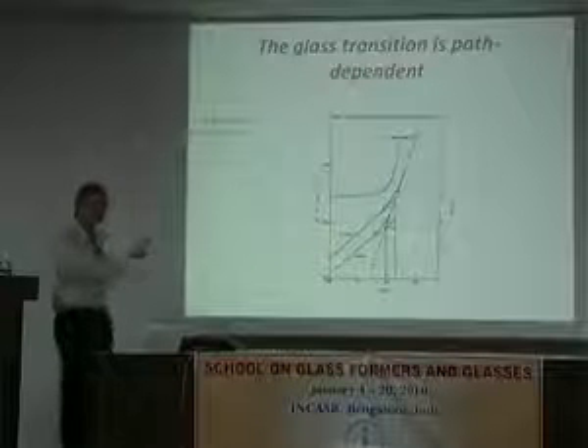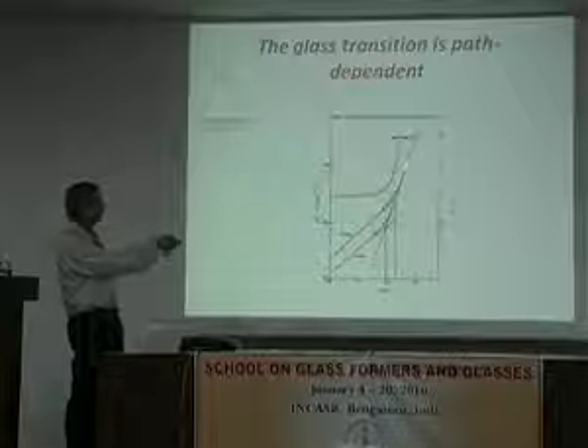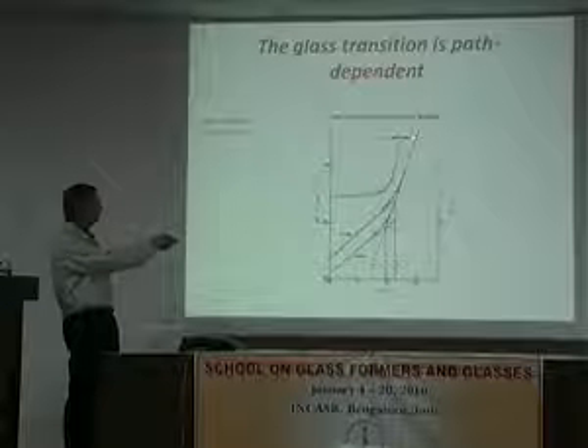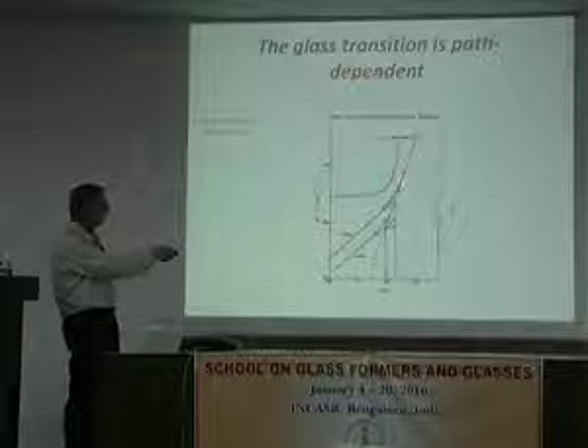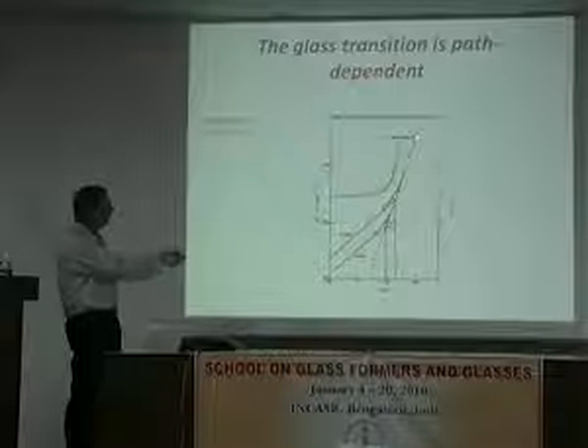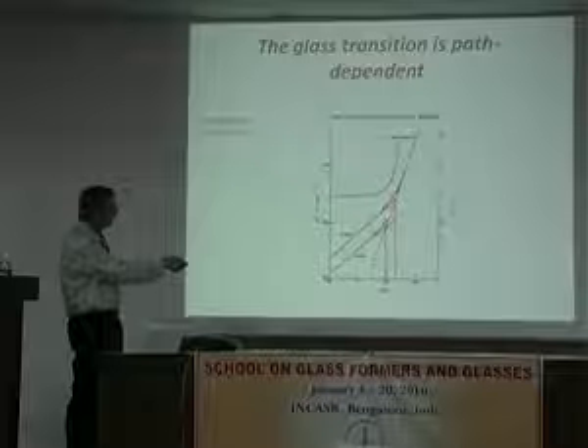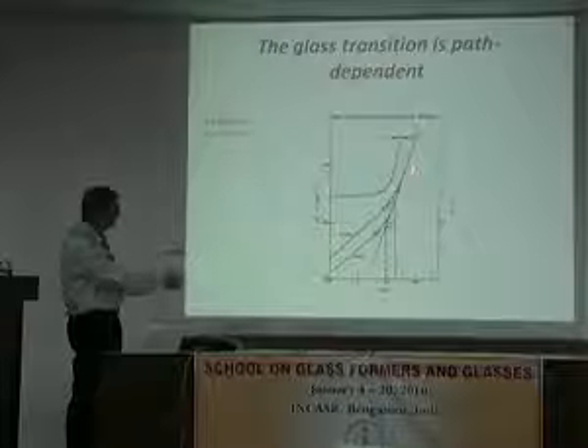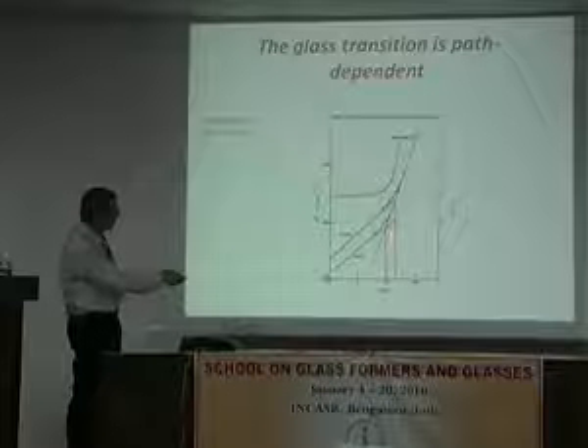Okay, but it would be equivalent in some of your glass formers to the supercooled liquid state. And what we see is as we cool the sample, of course, at some point we get a departure of the material from the equilibrium line, which is this line, and that point we call the glass transition temperature.